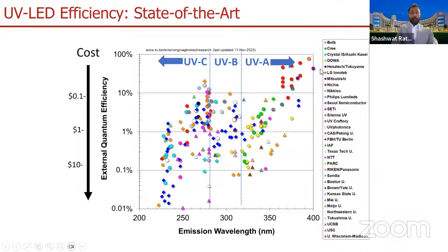So 400 nanometers is close to blue LEDs, right? So this is what the three Japanese Nobel laureates achieved, a highly efficient blue LED. But as soon as you come down in wavelength, you see that there is a drop in UVA, UVB, and even UVC. All of these are only single digit percent efficient right now.